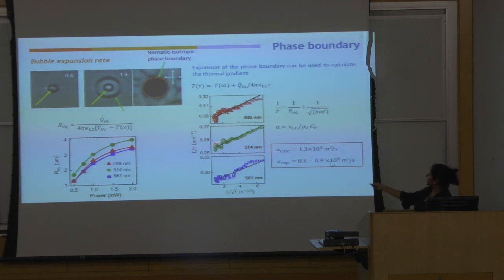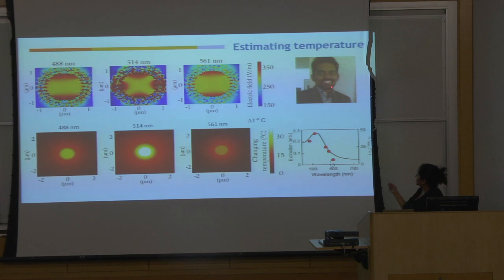We calculate alpha, get alpha with our guess in here from experimental data, and see if they match. They don't match entirely, but they come really close, which means our estimate of how much energy is absorbed by one shell is not orders of magnitude off. Now that we guess this one or estimate this one correctly, we can now map the temperature of the shells. And we do this. This was done by Som, who's a current grad student. We do some FDTD imaging to do the electric field scattered on the surface, and we map the temperature.